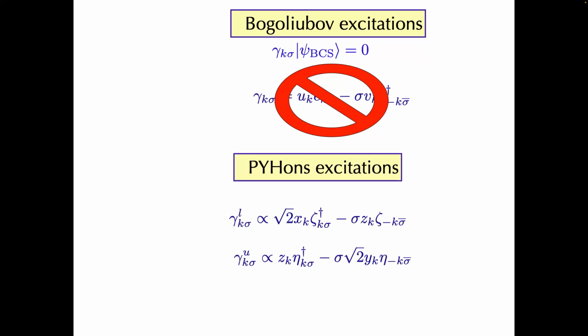So the superconductor you go to is not a BCS superconductor if you start with a Mott insulator. And one of the things this linear combination can explain is this transfer of spectral weight from high to low energies that's seen in the van der Marel experiments and the optical conductivity. The moment the system superconducts, there's a color change. And the reason there's a color change is that even the upper Hubbard band is also getting gapped.